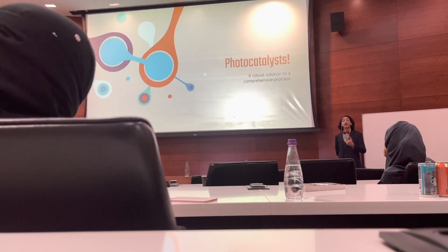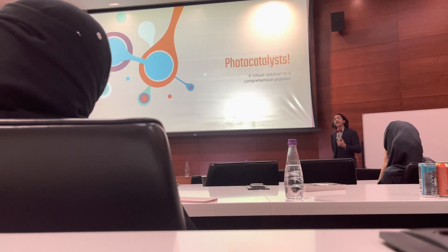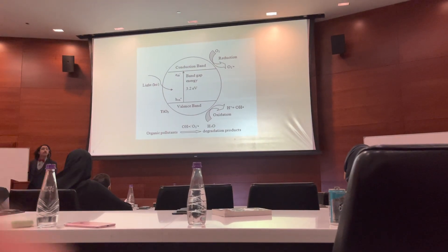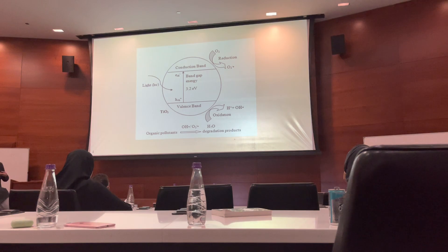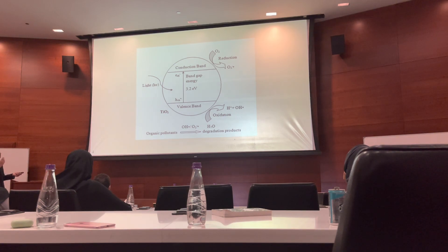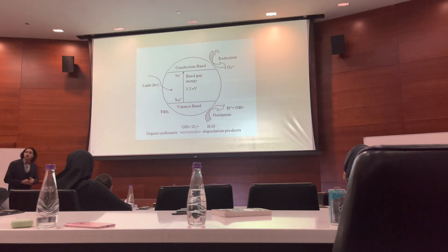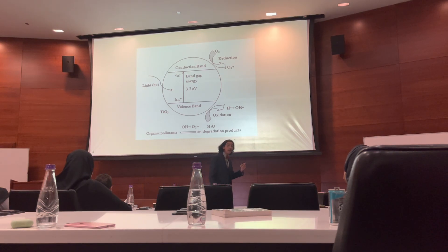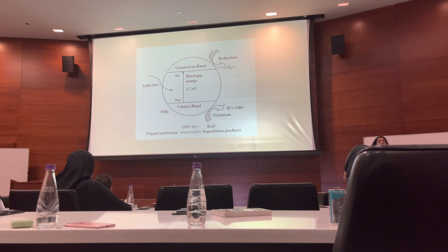Using light to drive a specific chemical reaction, we can accelerate the degradation of organic dye pollutants. Photocatalysts work by exciting electrons — you have a material, in my case metal oxides, and you strike it with a photon of light. That excites electrons from the valence band all the way up to the conduction band, where the electron is free to undergo a wide range of chemical reactions, including the degradation of organic dyes.